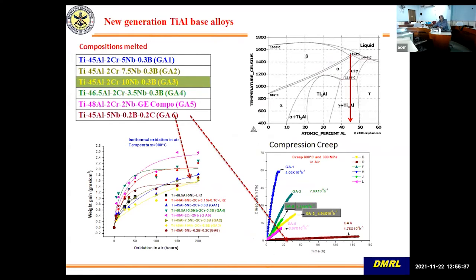These are certain compositions. I'm not going into too much detail. We can talk about it. This is the GE composition which we have melted, and also other variations. People are going down in aluminium content, and they are adding other elements. And this is the oxidation resistance of these alloys as compared to the GE composition. Our alloys have got much better oxidation resistance, and one alloy has got very good creep resistance as compared to the GE composition also.